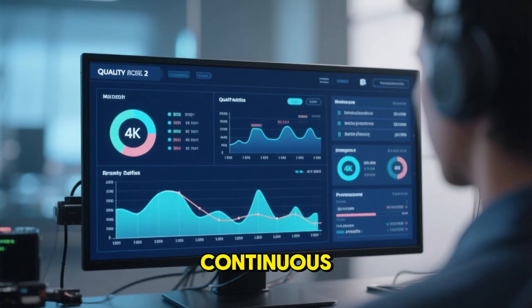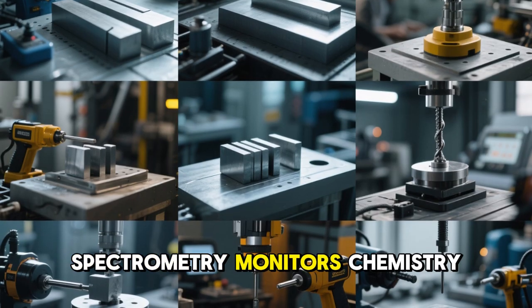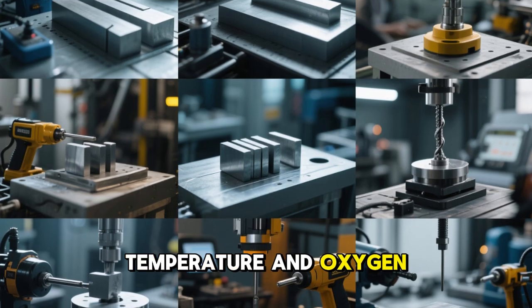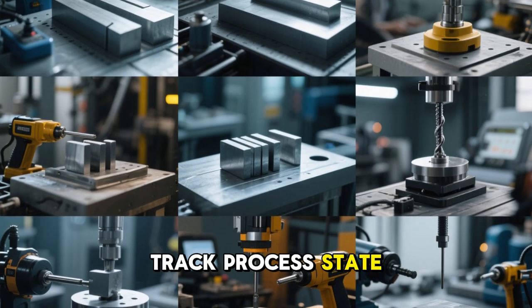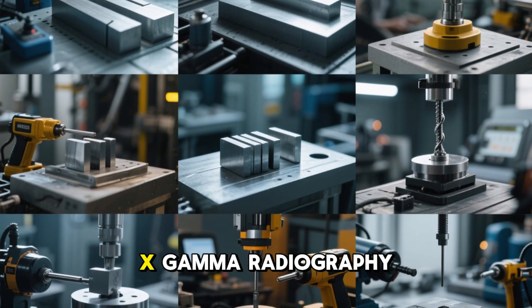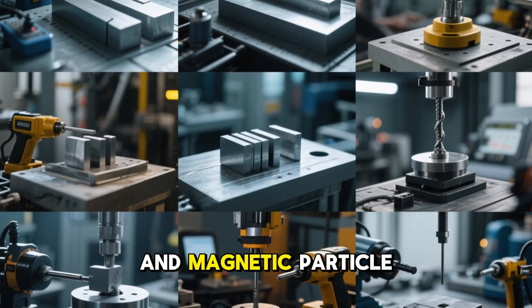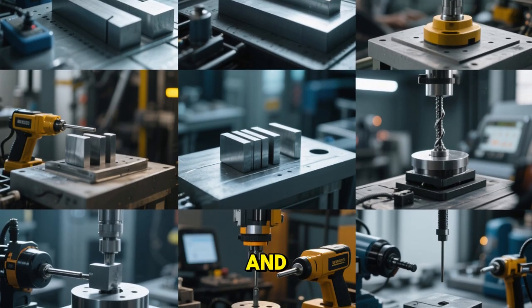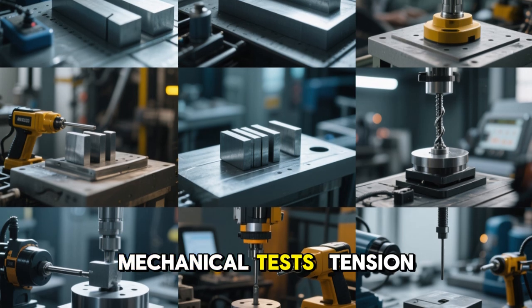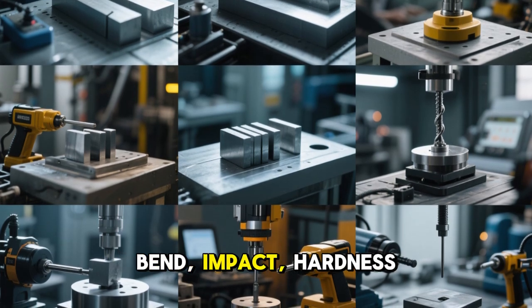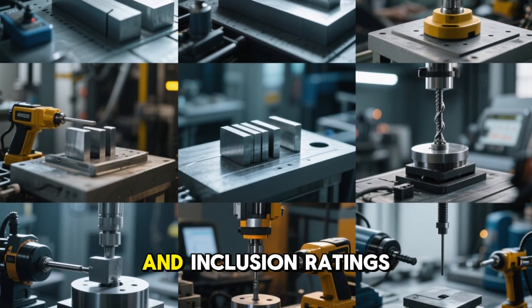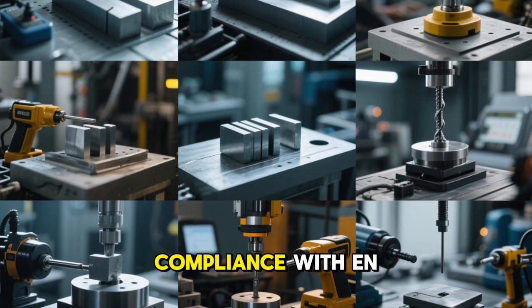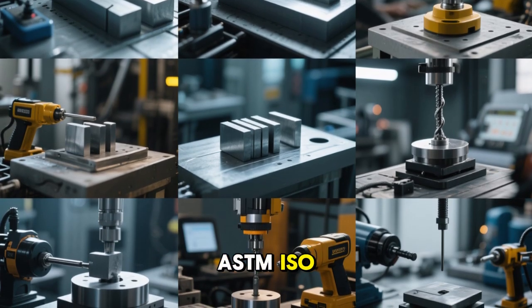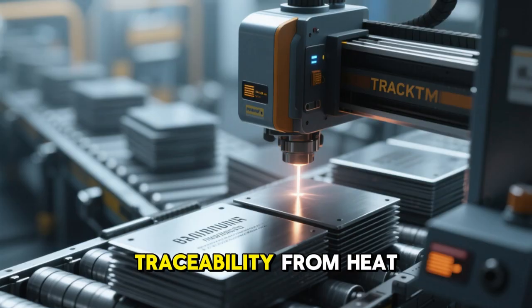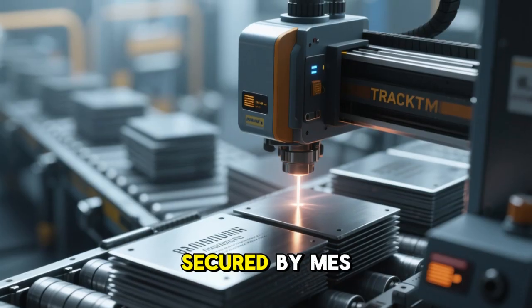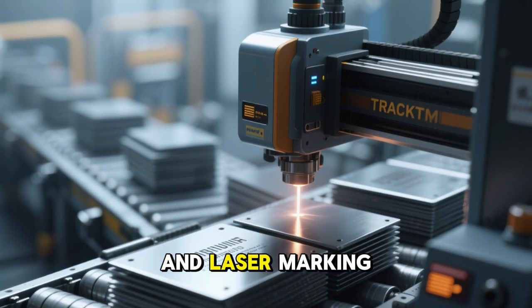Quality control is continuous. Spectrometry monitors chemistry, temperature and oxygen probes track process state, ultrasonics, eddy currents, X-gamma radiography, and magnetic particle tests detect internal and surface defects. Mechanical tests, tension, bend, impact, hardness, metallography, and inclusion ratings verify compliance with EN, ASTM, ISO, and customer specs. Traceability from heat to coil or bar is secured by MES systems and laser marking.